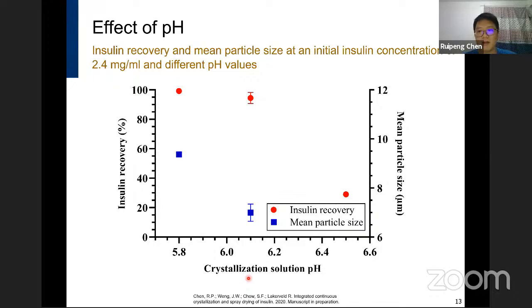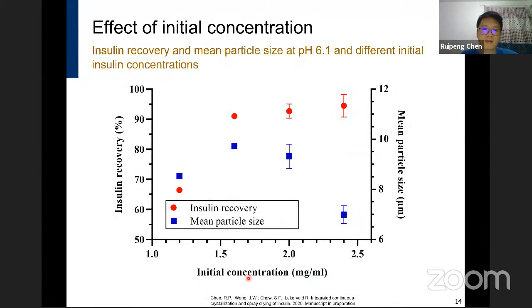Then we decided to conduct the following experiments at pH 6.1, because this one has a high recovery and also a small particle size. So we can look at the effect of initial concentration, which we performed at pH 6.1 and different initial concentrations. The trend is similar to the pH.